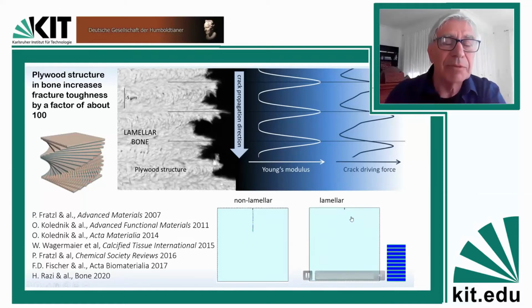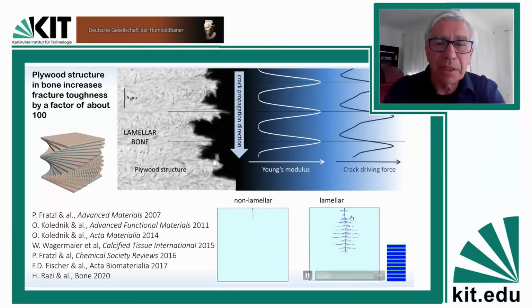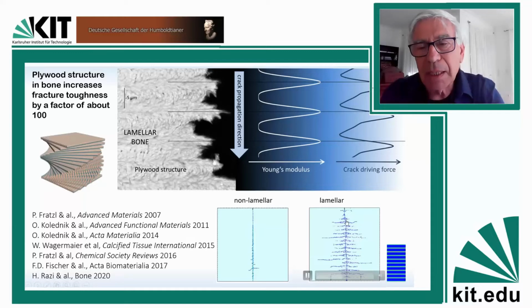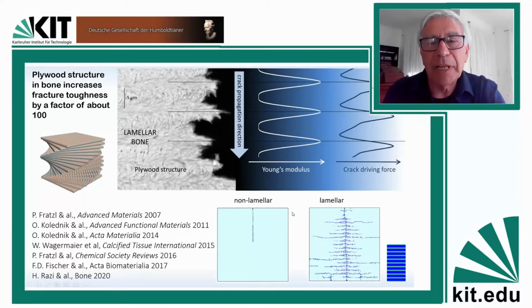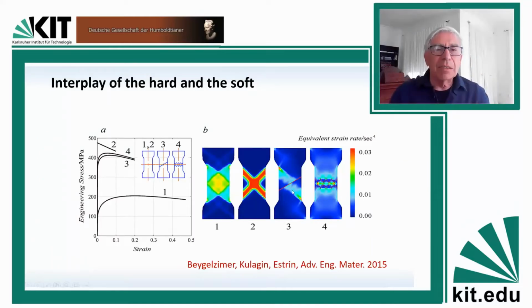So from this, even if in an engineering structure we cannot directly mimic this design, we can at least get the idea that having a lamellar structure and playing with hard and soft gives us great benefits. And in a simple example, we just wanted to demonstrate this in a standard material which is ductile, material 1, and a hard, ultra-fine grained material, which are usually strong but pretty brittle. That's the stress-strain curve of this brittle material. And if you just take this brittle material and have one single layer of a soft material, you get, so the material 1 is ductile, the material 2 fails